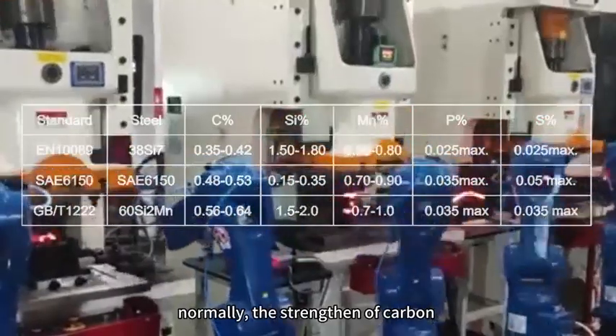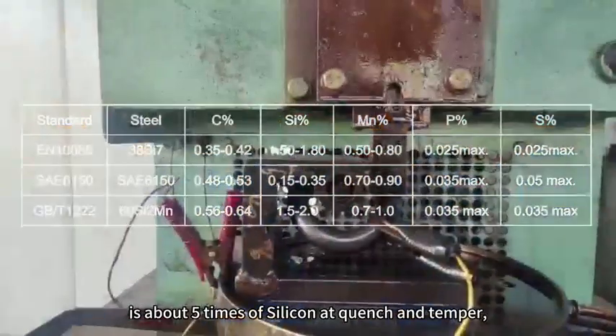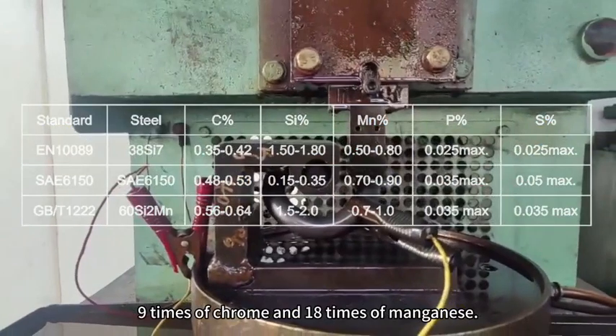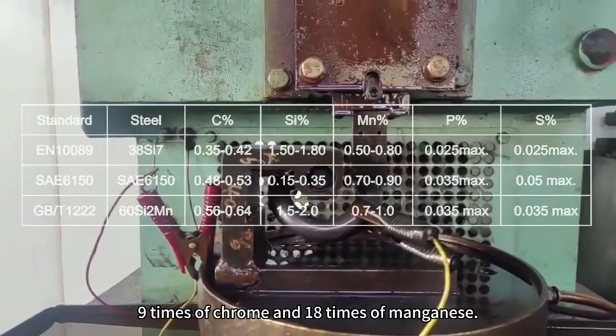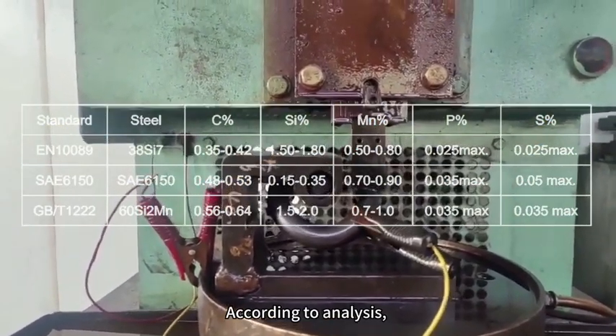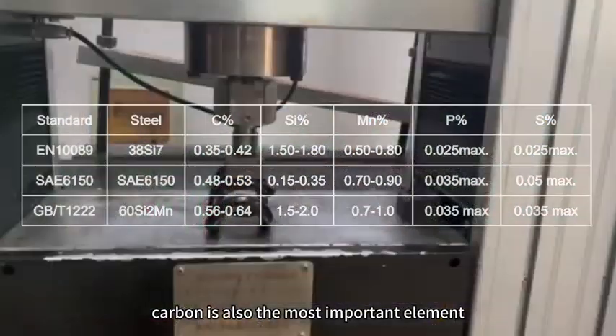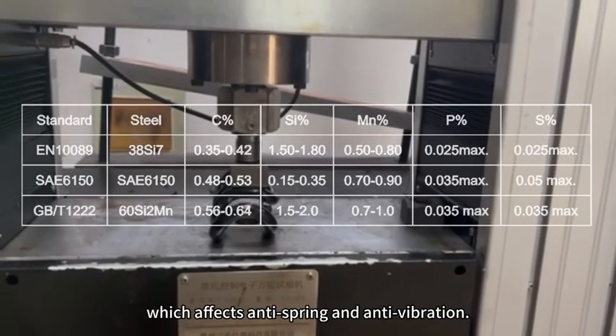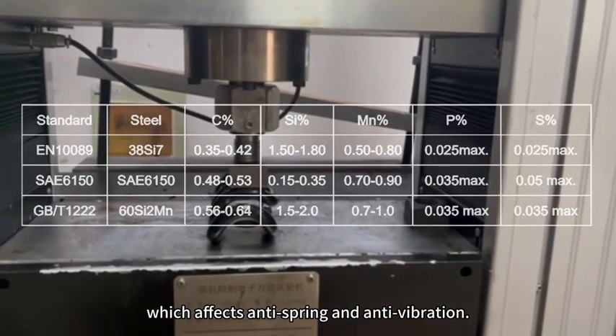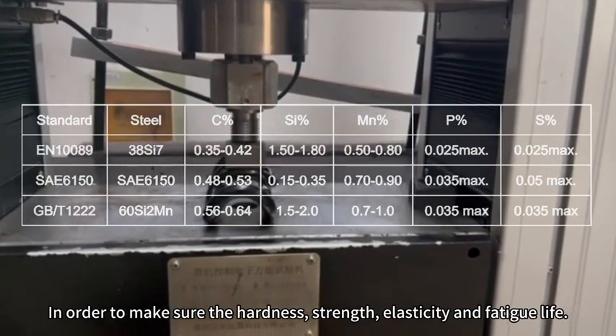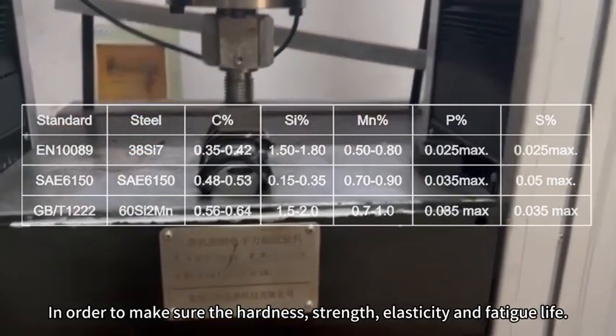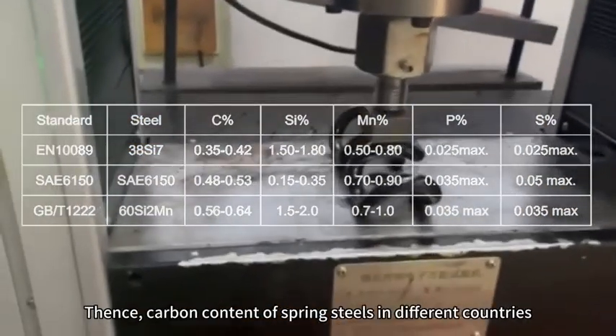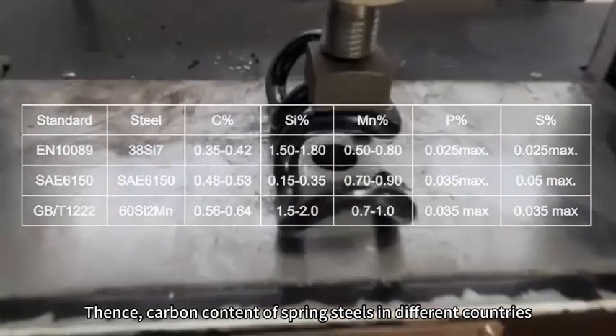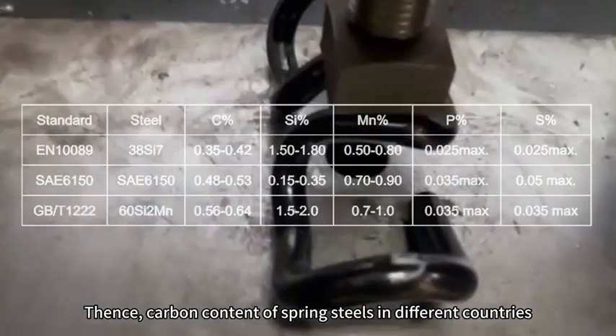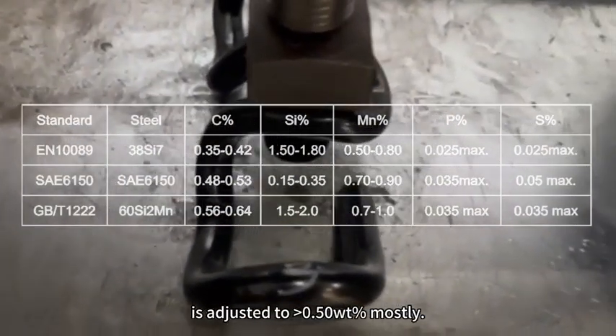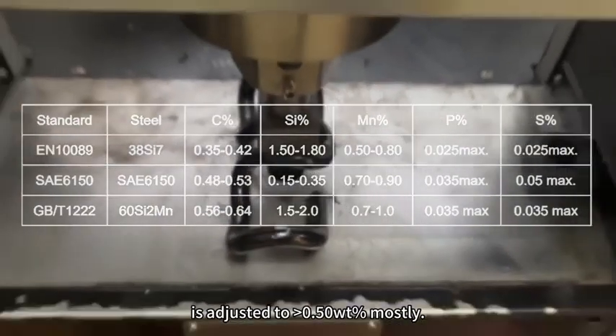Normally, the strengthening effect of carbon is about 5 times that of silicon, 9 times that of chrome and 18 times that of manganese at quench and temper. According to analysis, carbon is also the most important element affecting anti-spring and anti-vibration properties, in order to ensure hardness, strength, elasticity and fatigue life. Thus, the carbon content of spring steels in different countries is mostly adjusted to 0.50 Wt%.